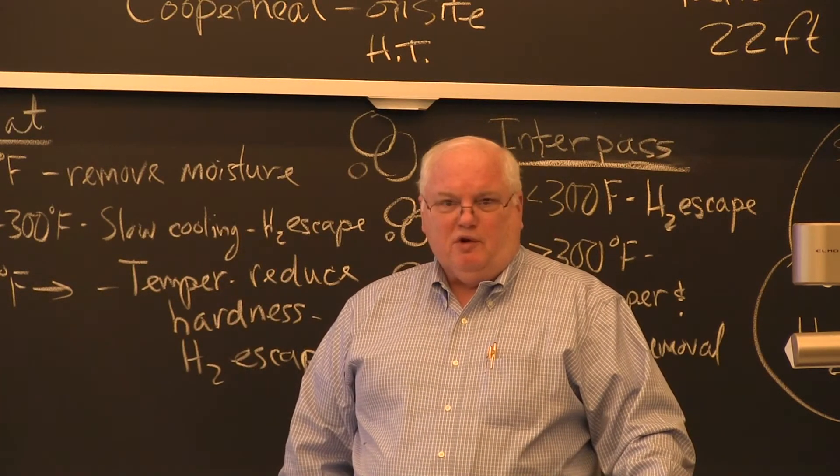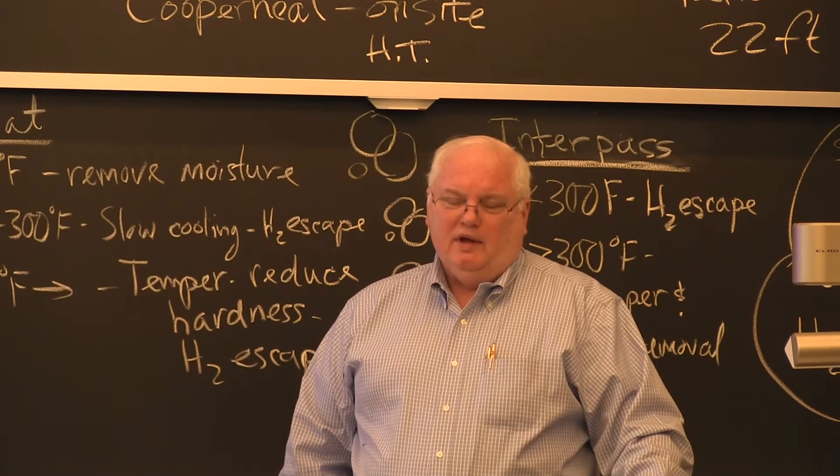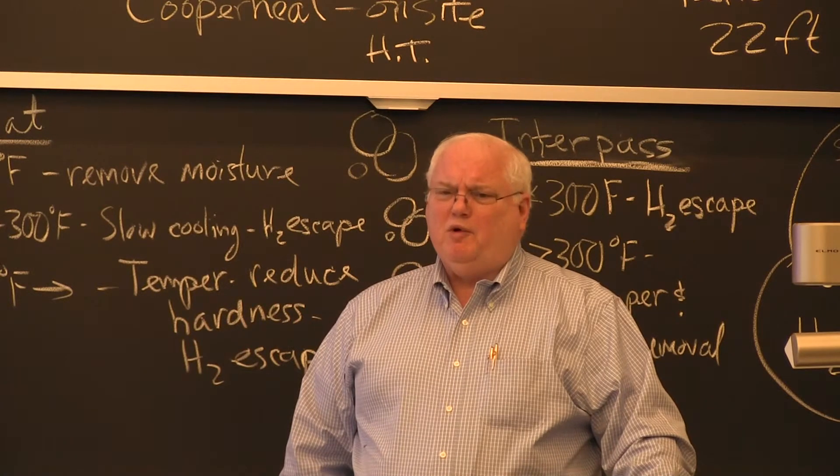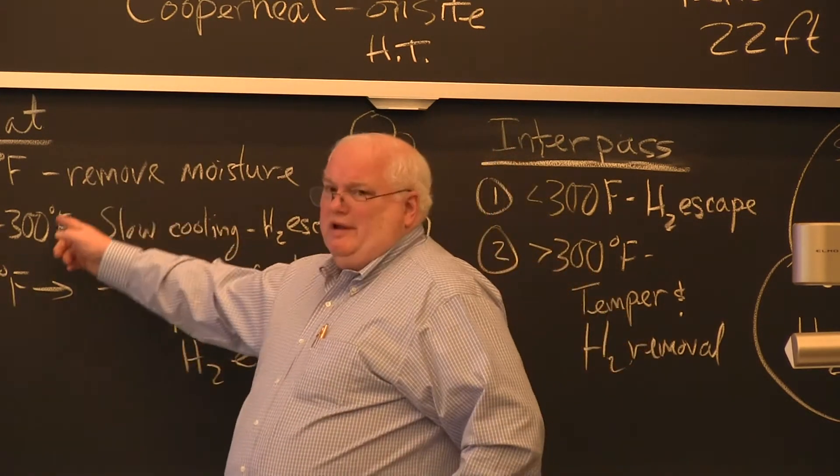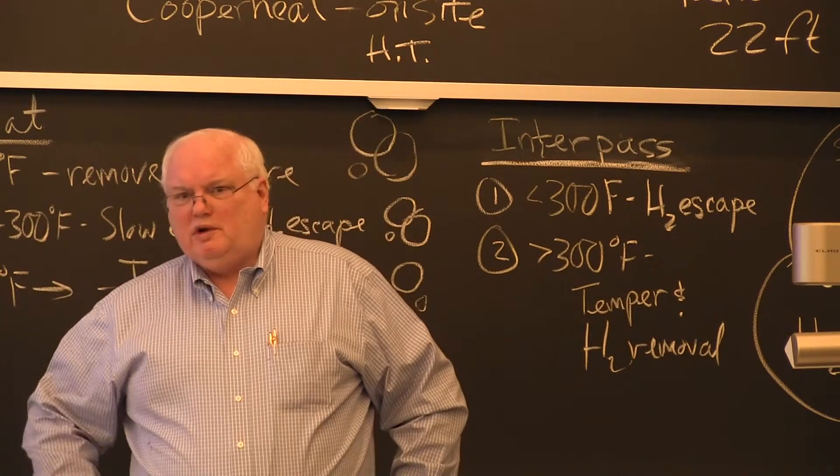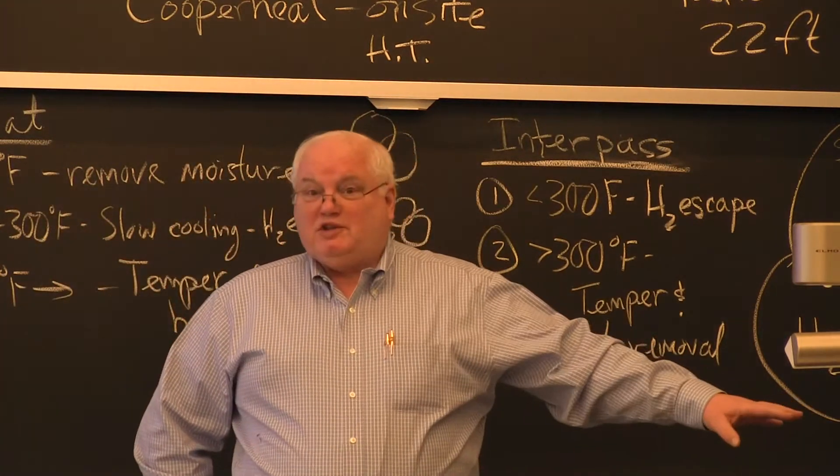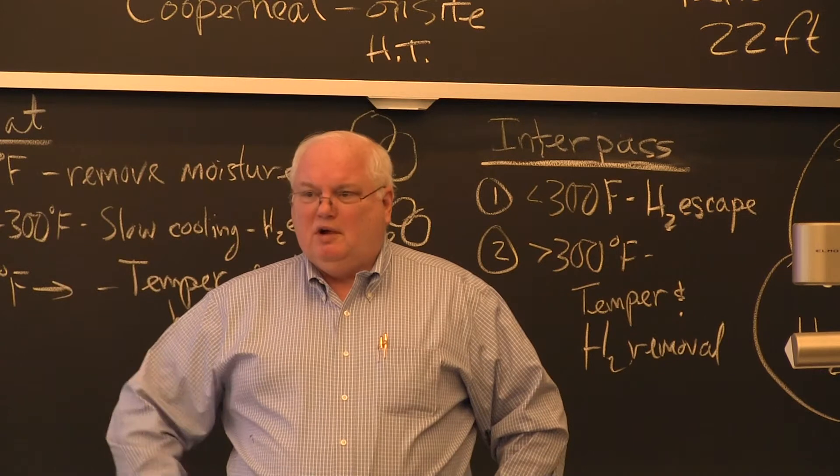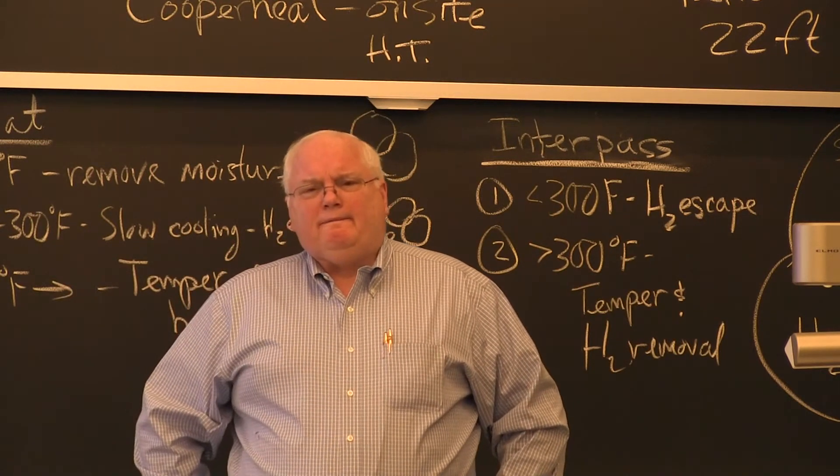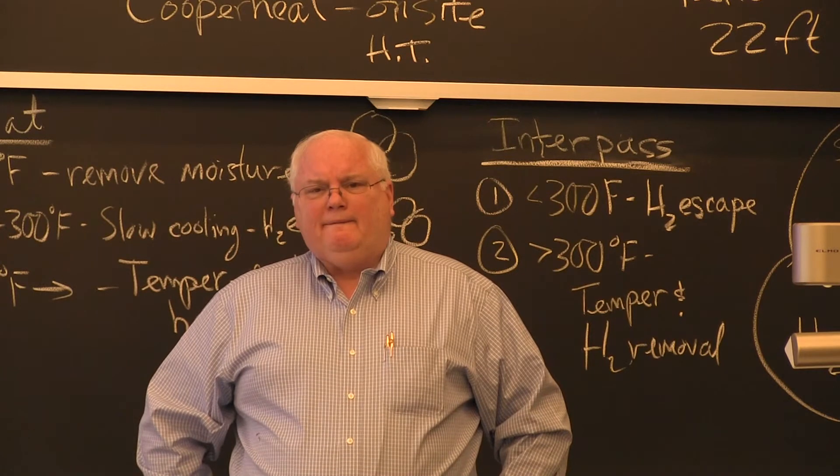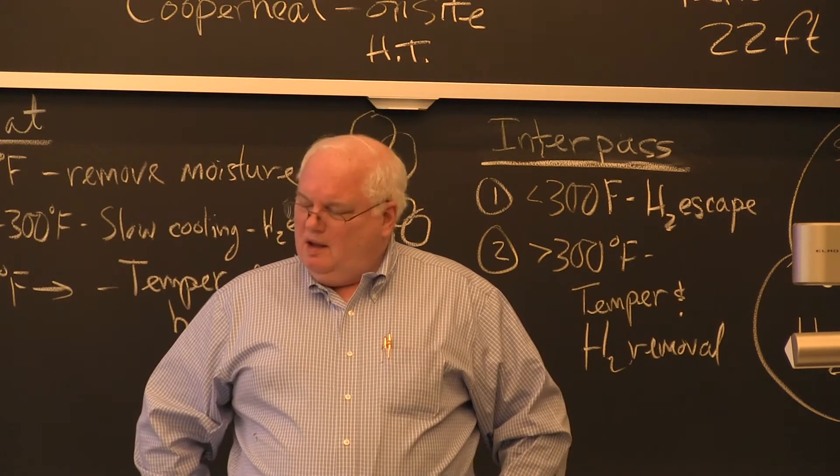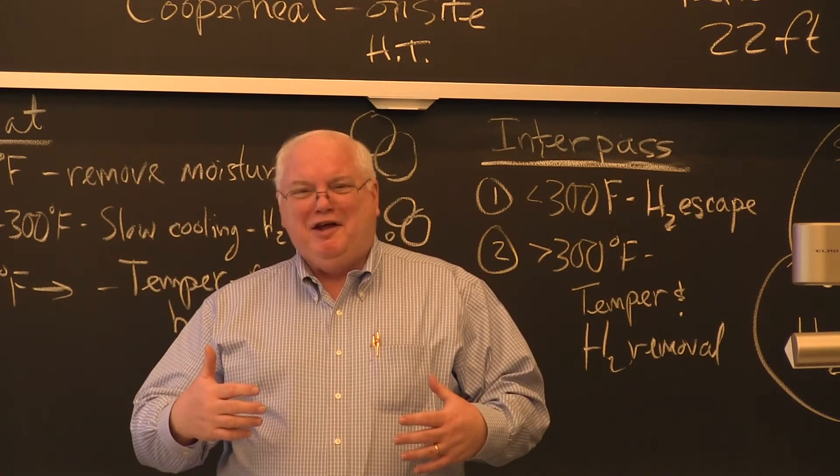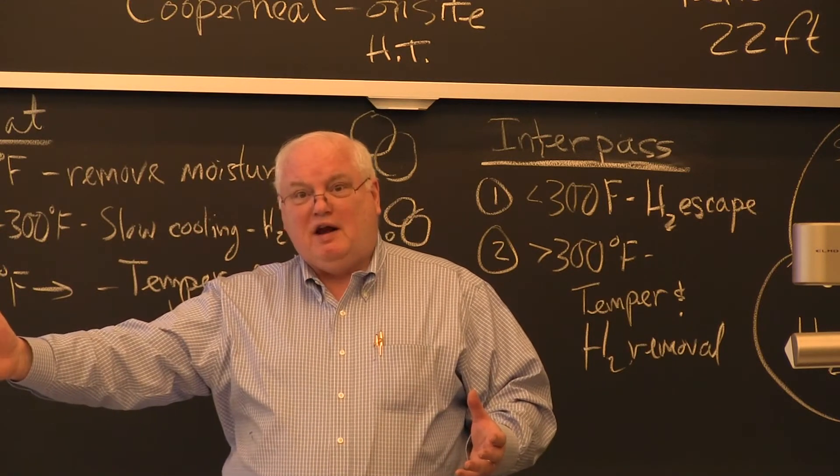Well 4340 is clearly in zone 3, and so I had to develop a welding procedure for them for 4340. I went over to see, and 4340 I don't remember but it was probably a 600 degree F pre-heat, and I may have included post weld heat treatment, I don't remember all the details. But I picked up Stout and Doty, picked up 4340, saw what they recommended, and kind of worked things out from there about what welding might go there. When you have a 600 degree pre-heat, are you actually having guys weld or is it robotic? At that point you have people standing right there. Now they may be wearing heat reflective suits.